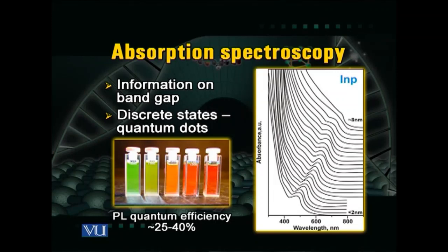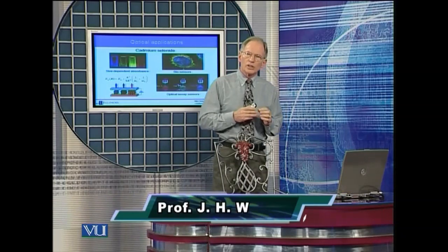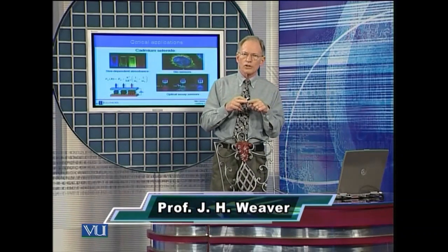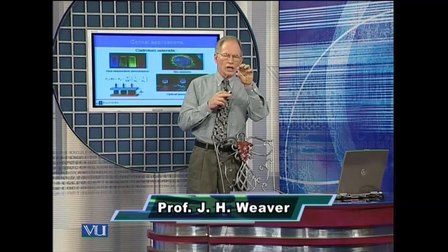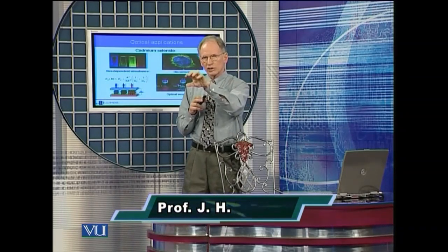And then if I look at the colors that are emitted after a photon is absorbed, that is photoluminescence, I see green and yellow all the way to red, all the way across the visible spectrum. That's because of the size of the particle. And I can control the size of the particle. Now, why that might be interesting could be in a medical application. Suppose that I have a particular cellular structure where a particular part would like to interact with size A and the other part with size B, but I don't really know what the details are.